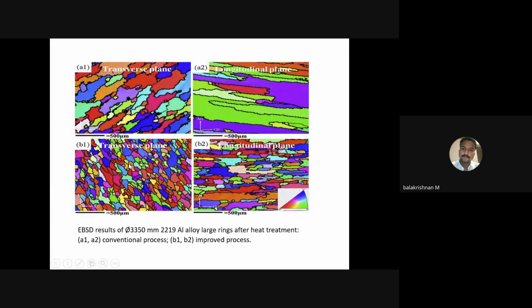Here we can see that according to the direction, that is the transverse plane and the longitudinal plane, the grain orientation is totally different, and the size of the grain also. Compared to A2, B2 is very fine. So we can attain maximum property in B2.